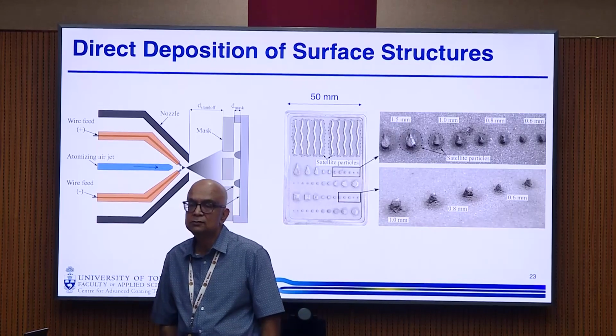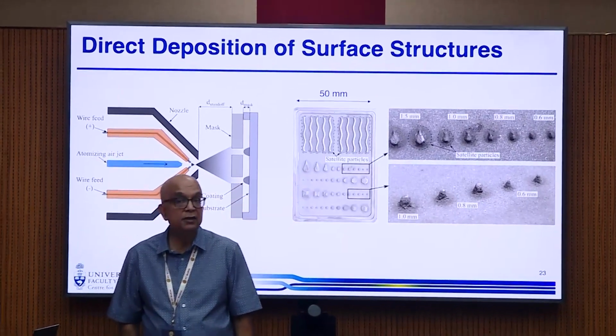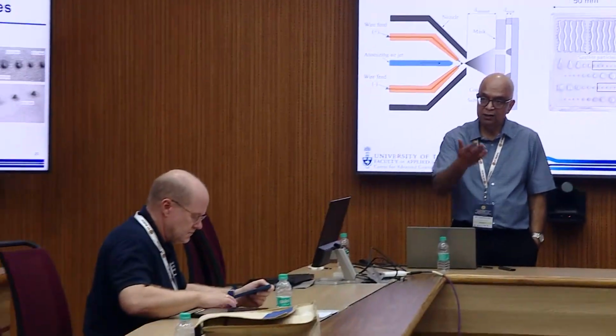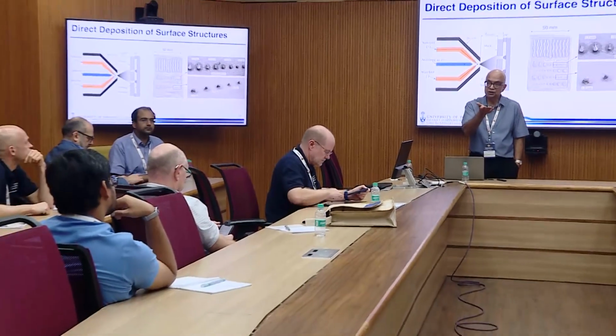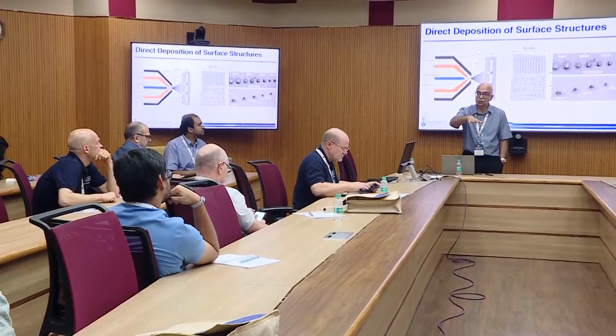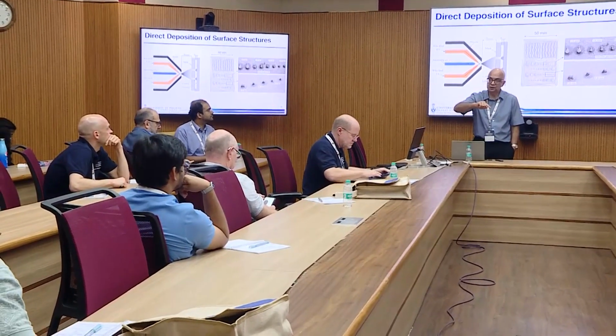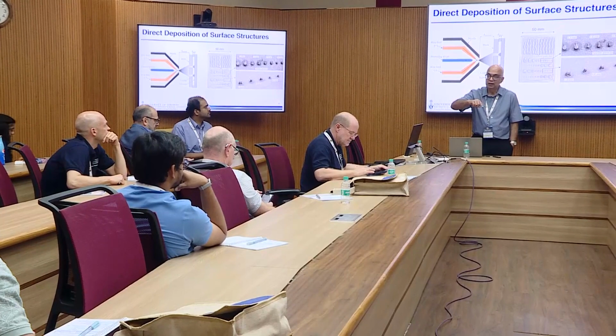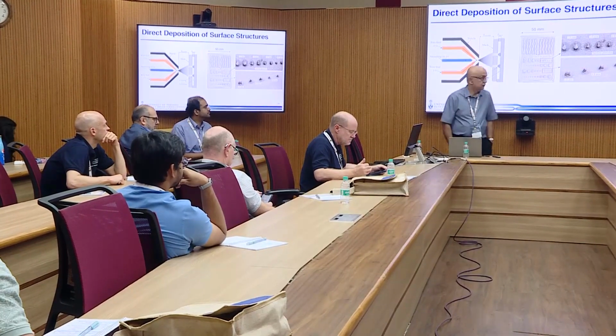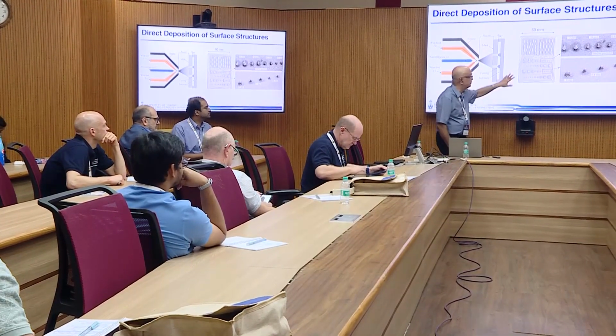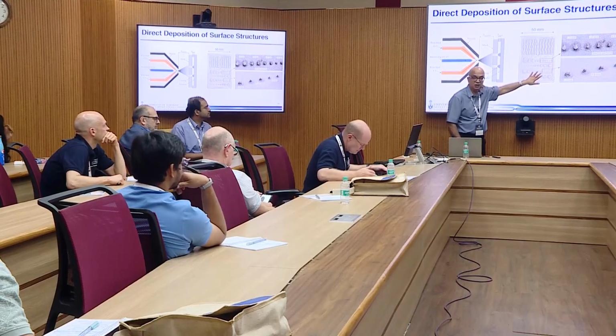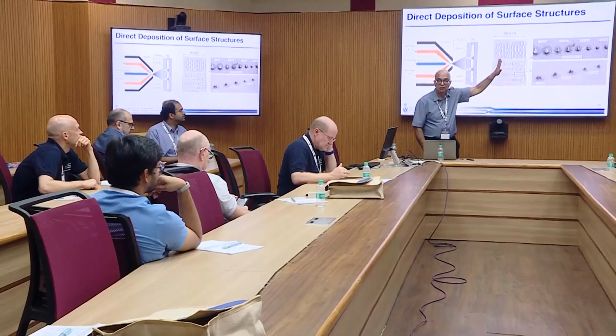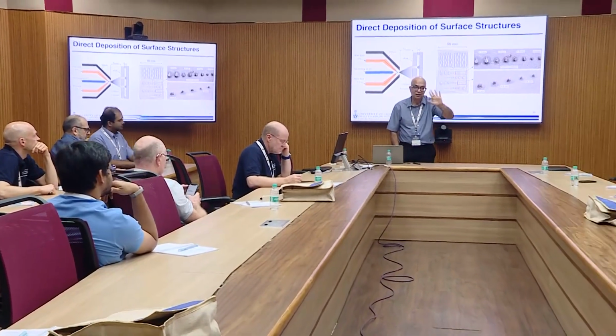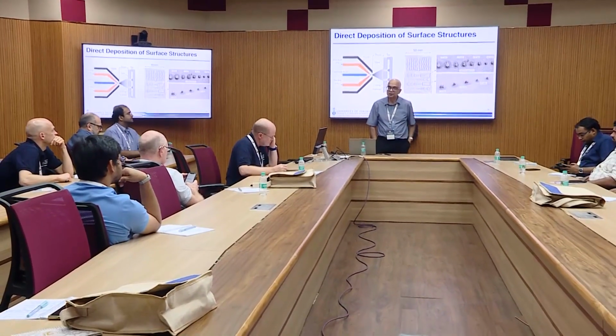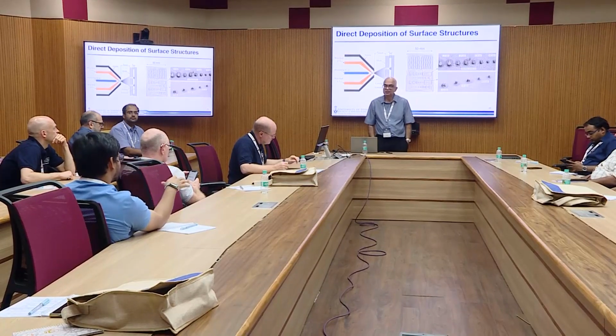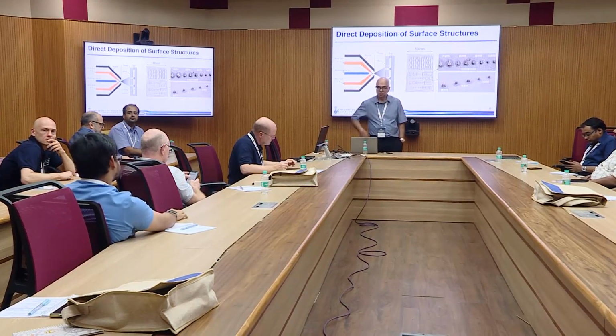How does the lid bond to these projections? It doesn't. But our heat conduction is from below, so it actually doesn't matter. The lid is just sitting on top, so it's pretty poor heat transfer from there. If you really wanted, we did one where we filled the whole thing with PVA paste and sprayed metal on top and then dissolved that paste, but that's messy and complicated. It doesn't matter because your heat transfer is from below.